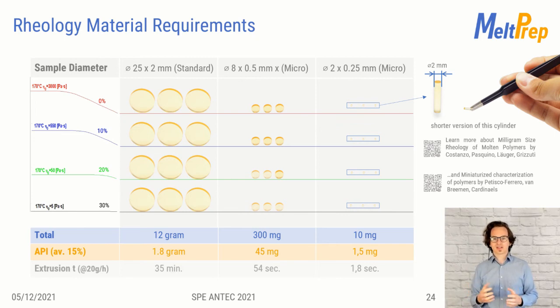Standard rheology tests are done 3 times for each API concentration. So 12 samples weigh around 12 gram with 1.8 gram of API loading. To reduce the amounts further, you can use microrheology. 12 samples with 8 millimeter diameter require 300 milligrams of material and only 45 milligrams of API.